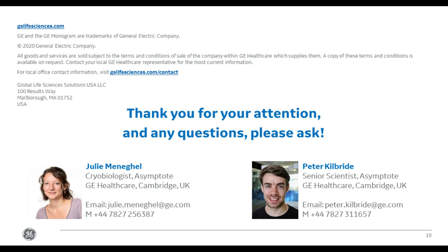And it's also important, we didn't really talk about it on the webinar that much, but talk about ice nucleation. The larger the volume, there tends to be less supercooling, it's called, before ice nucleation, and therefore that tends to be better for cells. So you might see a difference in ice nucleation. It tends to be a higher temperature in larger volumes, and some cell types are sensitive to that, and they find a larger volume, therefore better.